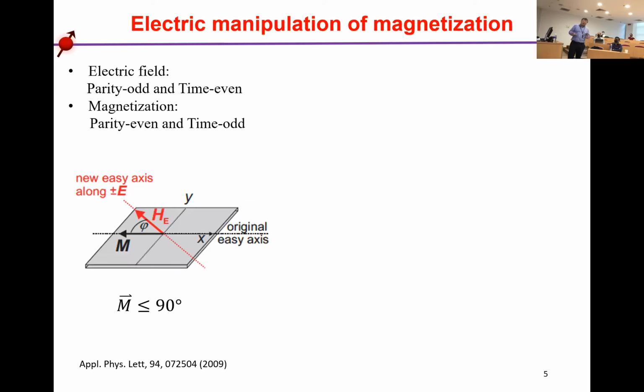So as people know, we commonly switch the magnetization by using a magnetic field, which is generated by passing current through a coil. In the early part of this century, that means after 2000, people started using the electric field to switch magnetization due to its energy efficiency, because with the electric field there's no current and no Joule heating. But when we do some symmetry analysis, we found the electric field is parity odd and time reversal symmetry even. Whereas for the magnetization, the parity is even, but the time reversal symmetry is odd. So from here, we say the symmetry does not match. Therefore, it is impossible to purely use the electric field to switch the magnetization by 180 degrees.